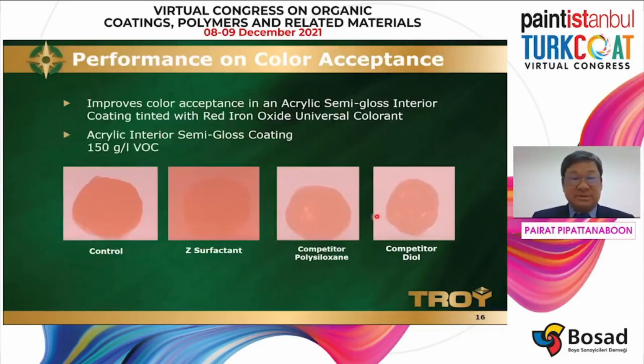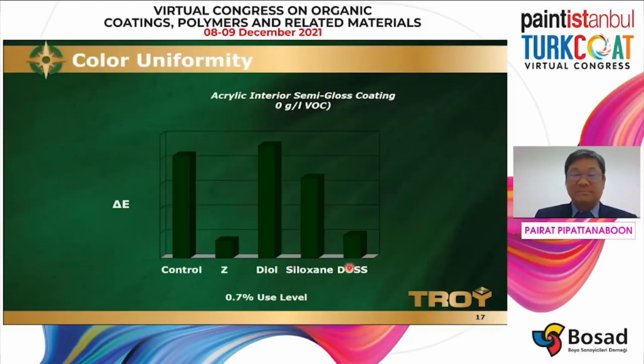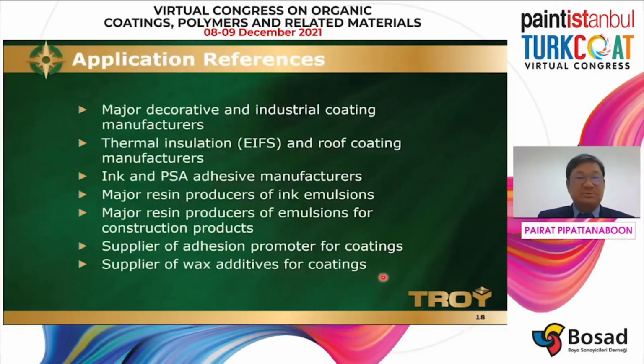From the picture you can see this is the formulation that we discussed before, tinted with red iron oxide universal colorant into the white base acrylic semi-gloss interior. After the rub-up test, we check delta E, and you see that this formulation helped to control delta E, or color acceptance, compared to the polysiloxane and diol. Another formulation, acrylic interior semi-gloss, 0 VOC, same thing: the delta E from Z helped to control the lowest delta E, or improve the color acceptance, compared to diol, siloxane, and dioctyl sulfosuccinate at 0.7% use.